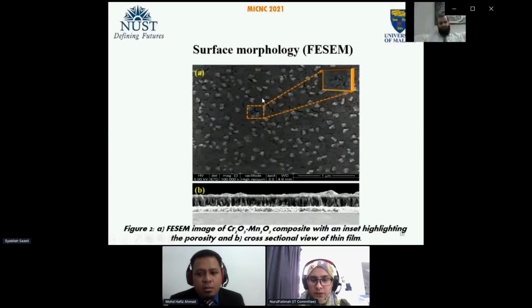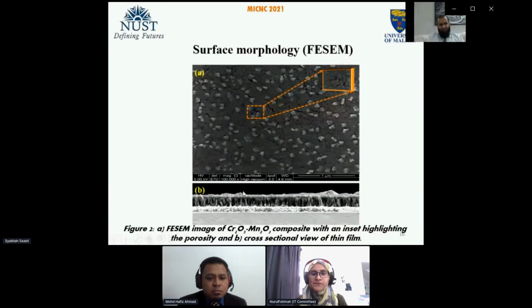Similarly, the surface morphology was studied by FESEM, and it shows that the manganese oxides are producing nanorods. The rods are here, which are decorated with the cubes of chromium oxide, and they are well connected with each other, thus producing a synergistic effect. This synergistic effect leads to a low band gap of the chromium manganese oxide composite thin film. At the same time, the pores are clearly visible. This material is highly porous.